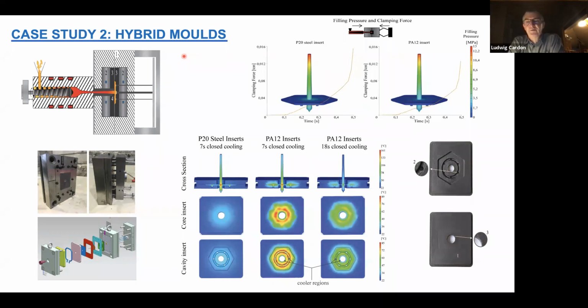We noticed ourselves that up to now, it can be used in the scope of what we call prototyping. So briefly to explain that, normally when you need prototypes, you go to 3D printing, you print your material, but it's not the real final quality you want to achieve, let's say polypropylene, ABS, whatever. So the big advantage of this kind of hybrid molds is you can produce these kind of molds: you design the insert, you produce them during the night. The day after you need some post-processing, and in something like 2-3 days, you have your mold.